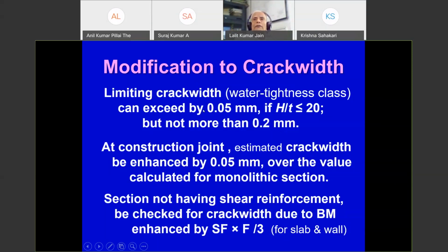At a construction joint, we know we are introducing weakness, not only in strength but leakages also. At a construction joint, the permeability increases, and we know it from experience that crack widths are higher. Unless you have a method of calculating crack width at a construction joint, there can be a method. While estimating crack width, we estimate the strain in steel and work out concrete stiffening. If there is a construction joint, concrete stiffening reduces, and that's how the crack width increases.